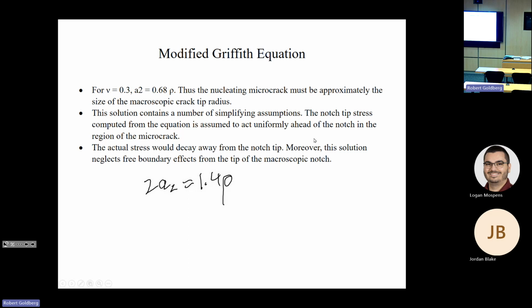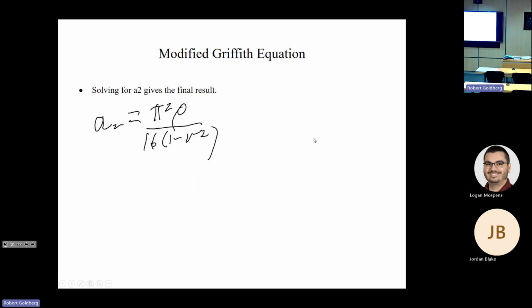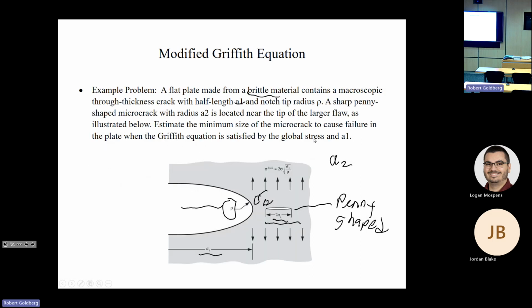The notch tip stress computed from the equation is assumed to act uniformly ahead of the notch in the region of the microcrack. In reality, you would have your maximum stress here, and then as you progress along, you would have a decrease in your stress. So your stress, exaggerating a lot, would be something like this. We just assume that the stress right at the tip stays constant all the way along the length. So that's a simplified assumption.